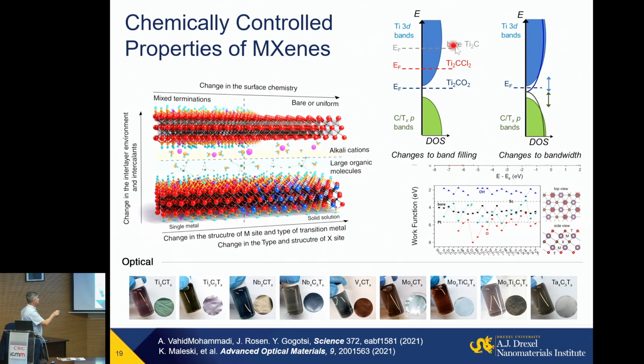I mentioned to you several times that MXenes are metals, the majority of them. So bare, all of them would be metallic. But what is interesting, the density of states is not as high as in gold or copper, which don't care when you do something to their surface and inject electrons. You can change it by changing surface termination. Like in this example, we can do it in situ. So we can actually modulate their properties, chemically and electrochemically or optically as well. So you have metals, but with properties that can be modulated, like in semiconductors. Our entire current electronics is using semiconductors for a simple reason: by applying a small potential, we can change and modulate their properties. We can do this now in metallic materials like MXenes. And I think it again opens numerous new applications.